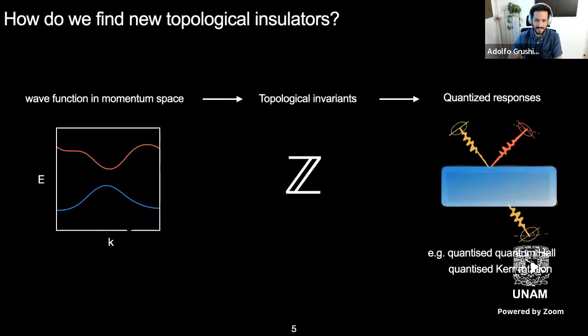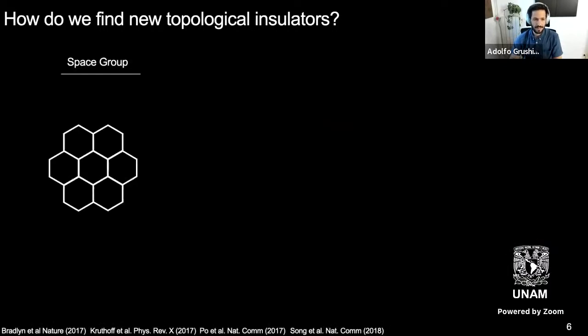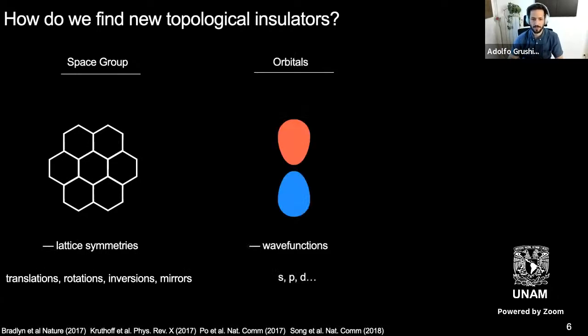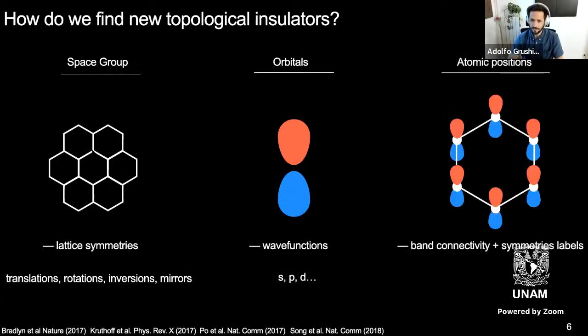So if I can label my states in momentum, I am implicitly using translational symmetry. But people went far beyond that and took more symmetries of the space group, which means all the lattice symmetries like translations, rotations, etc. Now if you give me the space group, you give me the orbitals you want to put in this space group, which means just the crystalline lattice, and where these orbitals are in real space, what you will draw is this band structure.